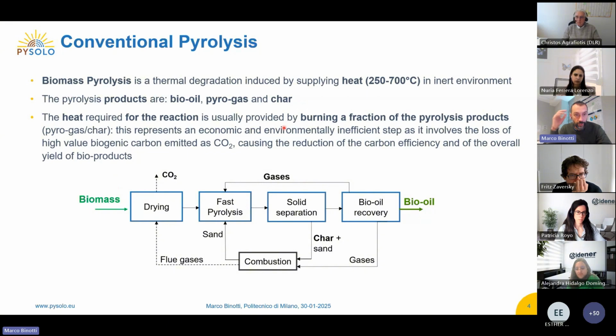But before speaking about the concept of the project, just a couple of pieces of information for those of you who are not familiar with biomass pyrolysis. Pyrolysis of biomass is a thermal degradation which occurs by supplying heat in an inert environment. This heat should be supplied at around 250-700 degrees C, with no air. Basically, the thermal degradation produces bio-oil, pyrogas, and char.